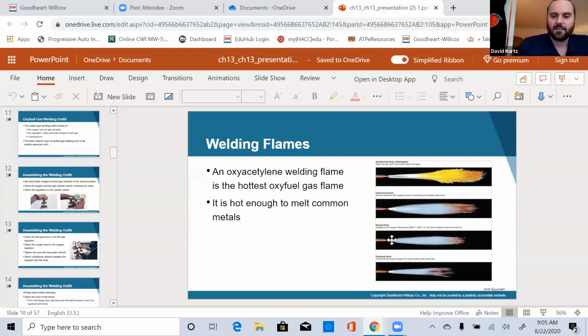flame. If you look here, after we've dialed in our flame with the needle valves on our torch, a neutral flame is this nice bright white cone, bullet-shaped cone, and then it has this blue tail to it with little to no flames at the end. When we first light the torch, we're going to get an actual flame like you would see on a lighter, and then as we steadily add in oxygen, that's when this flame is going to come down and start to get this blue look, and the oxygen is what's going to heat our flame and give it all that nice heat to melt our base metal.